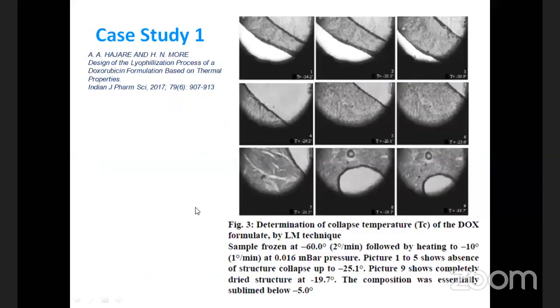So this is one case study which was published in one of the journals in 2017. This was related to the collapse temperature determination of a doxorubicin formulation using Lyostat. So initially the sample was frozen to -60 degrees Celsius at a ramp of 2 degrees per minute. And then primary drying was followed by heating to -10 degrees Celsius at 1 degree Celsius per minute at a pressure lower than 0.016 millibar.